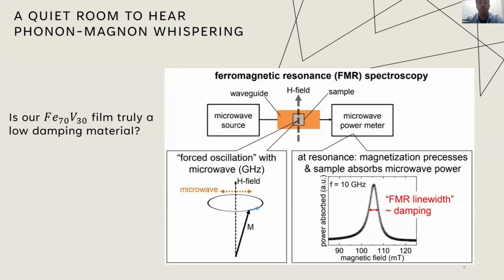We use out-of-plane measurement, which is ferromagnetic resonance spectroscopy. Let me briefly tell you what happens in FMR. The first step is that we place our magnetic sample in a microwave waveguide. Then we apply an external magnetic field, which makes all the spins align with the external magnetic field. But since all of these spins have angular momentum, they start wobbling around the field direction.